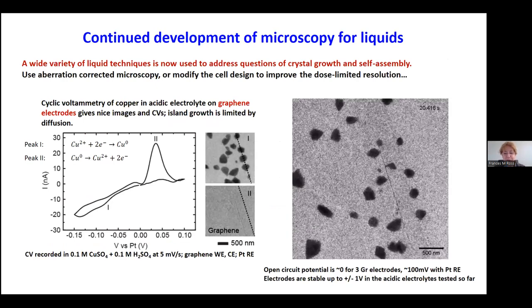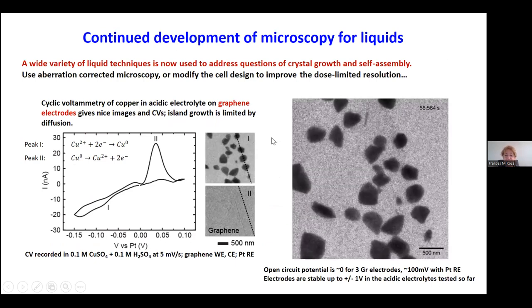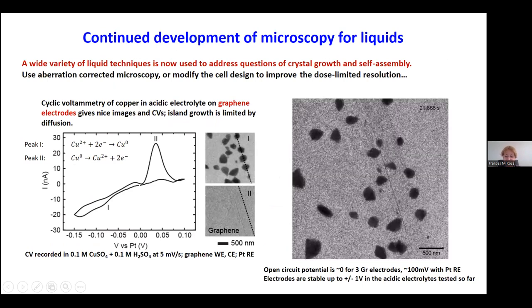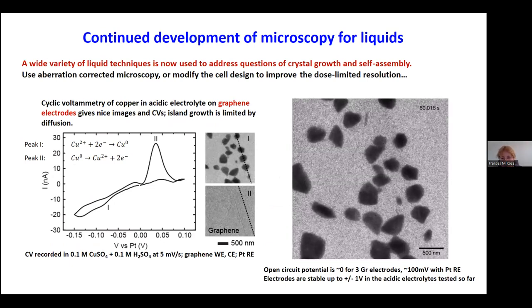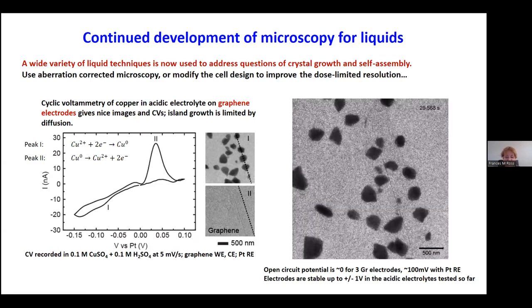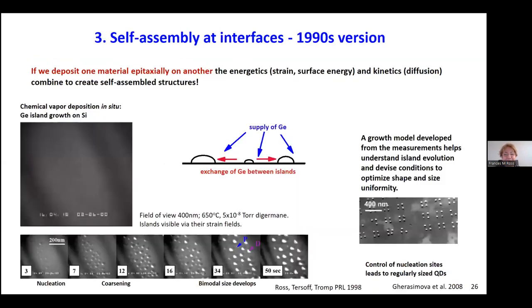There's a huge amount of development going on in the field of electron microscopy for liquids. I want to show one last example showing improvement of resolution compared to those early copper plating movies — the exact same process of copper deposition from acidified copper sulfate solution. You can see the self-assembly of beautiful faceted crystals much more clearly now that we're using a graphene electrode with much less scattering compared to the gold electrode used previously. Using modern equipment, modifying the cell design, and taking care with the dose to maximize information — electron microscopy of liquids is a huge area that is really exciting for understanding crystal growth physics.